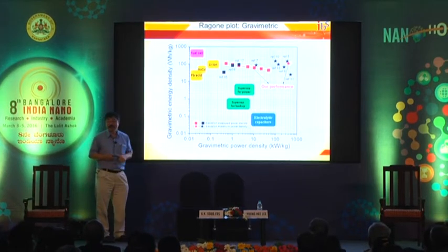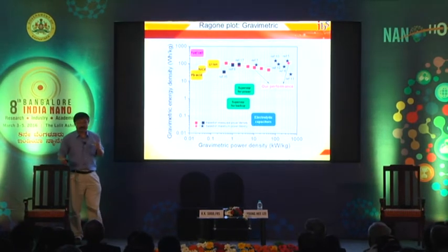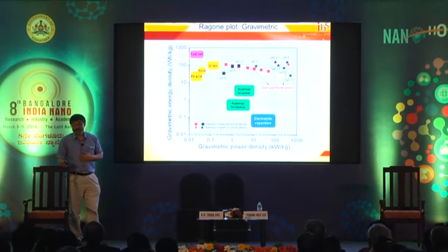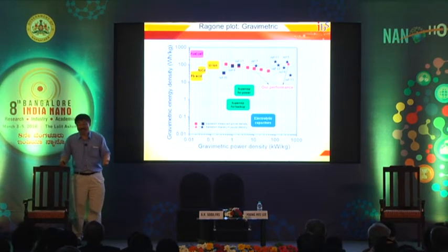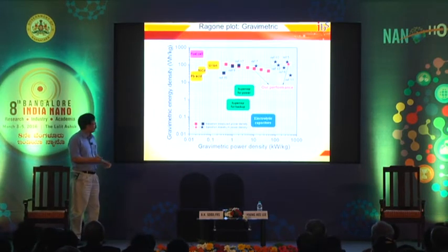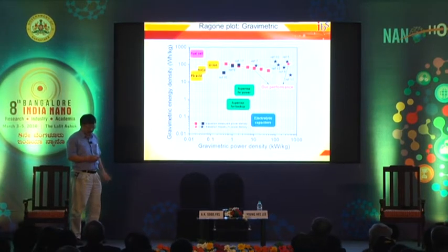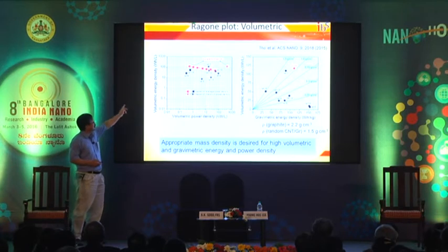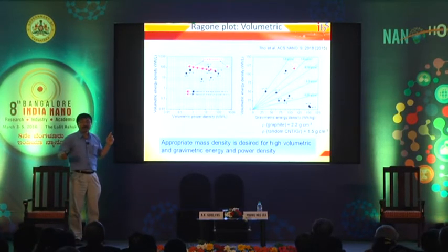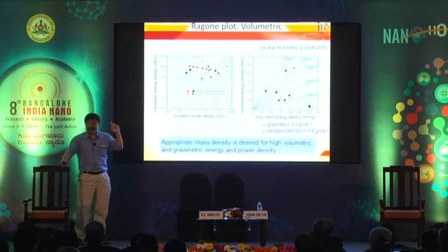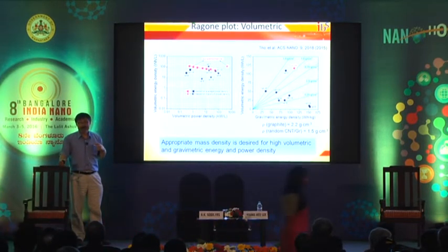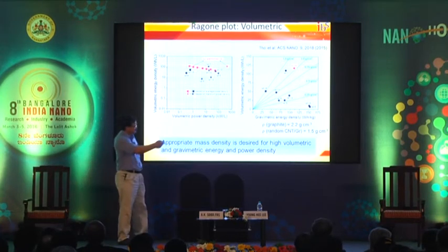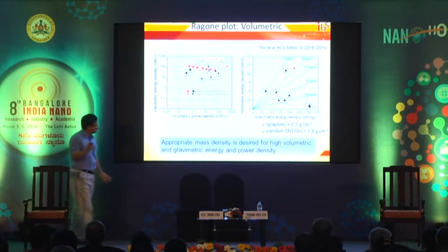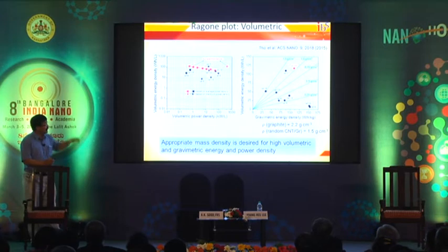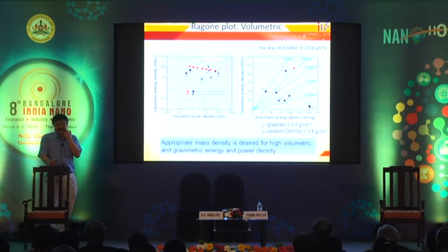watt-hour per kilogram. The best LIB, lithium-ion battery, shows less than 200. So we are already in the same order, and it's very good. And this is not only gravimetric. If you look at the volumetric, we still maintain a high value. The reason is that we have a very high mass density instead of a highly porous structure. This is the key. So you see our value is here. I think we are now working with a company to commercialize this.